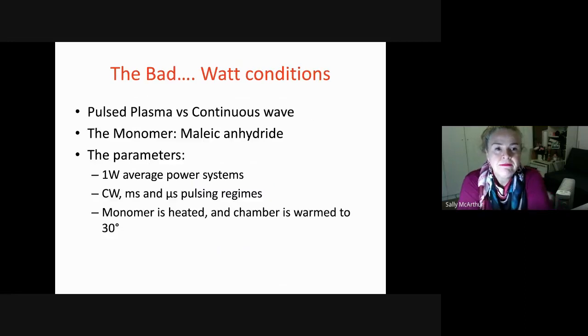So what we wanted to look at in this study was maleic anhydride. It's quite a complex chemistry. It's a ring opening to get it to polymerize, and that's the classic way that you polymerize it nicely. You get a film, but you have no anhydride reactivity in the actual film. For a long time, people had been debating what the right conditions are to do it in. So we did a study on the same average power in the system, 1 watt, but we wanted to look at different pulsing regimes and different power delivery. So continuous wave power, either a millisecond or a microsecond pulsing regime.